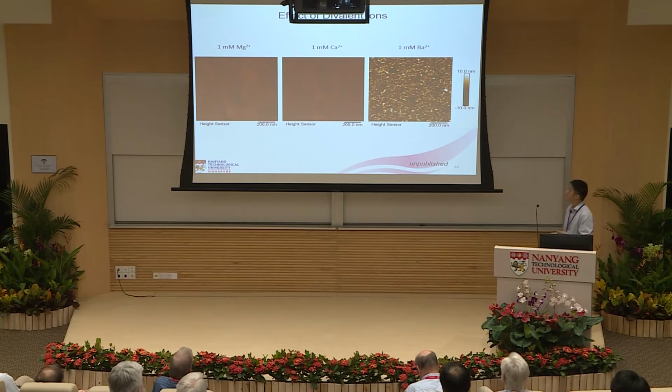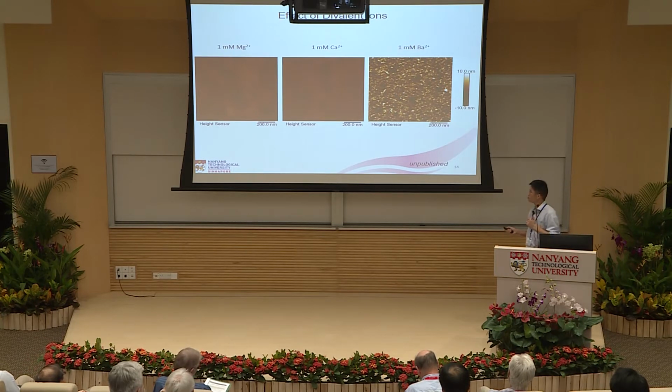The effect is definitely not only limited to trivalent salts. Here, I just started to measure the effect of divalent salts, so those are very new results. We see that in the presence of divalent counterions, the brush also collapses, although you observe much stronger ion-specific effects with different divalent ions. With barium, we get a structure similar to trivalent salts. And with magnesium, the surface profile is closer to a monovalent salt solution.